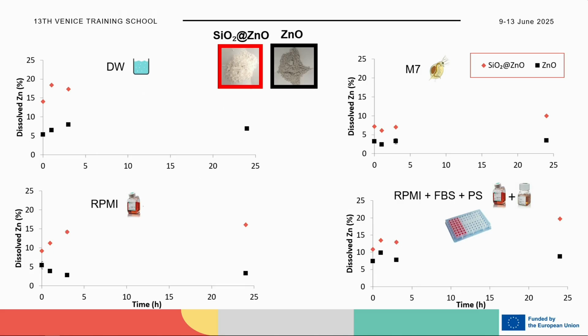And what we observe here, so you have different media in these 4 graphs, we look at the zinc dissolution over time. What we observe is that the dissolution of zinc, of course, this was normalized on the same concentration of zinc, was higher if we consider the advanced material with respect to the zinc nanoparticles. This probably was related to the different structure, actually, of the material, because on one hand, we had this very thin layer of zinc oxide around the core of silica dioxide. On the other hand, we had just quite larger nanoparticles, the zinc oxide nanoparticles, that were, as you remember, between 100 and 200 nanometers.